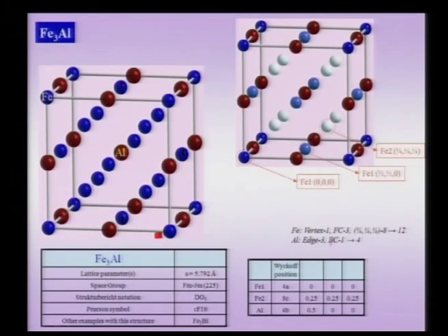Then we have this other iron atom which is located at the quarter position. So, this is the quarter position, and if there is one here, according to the face centering and the symmetry of this point group and the space group, we will see that there has to be an iron atom here, the 4-fold will take it here, there will be one more here, there will be one more here. So, this will be a position like quarter, quarter, quarter; the second position will be a quarter, 3/4, quarter. So, therefore, you will have other positions, and there you will have 8 atoms within the unit cell. Therefore, all the 8 which are contained within the unit cell will go as contributions to this unit cell. They will have 8 iron atoms located in this quarter position and other equivalent positions.